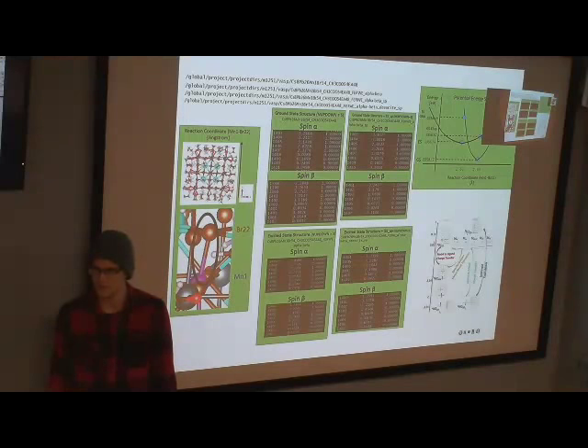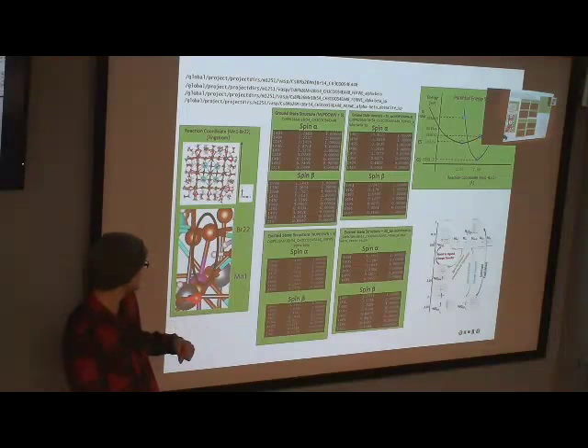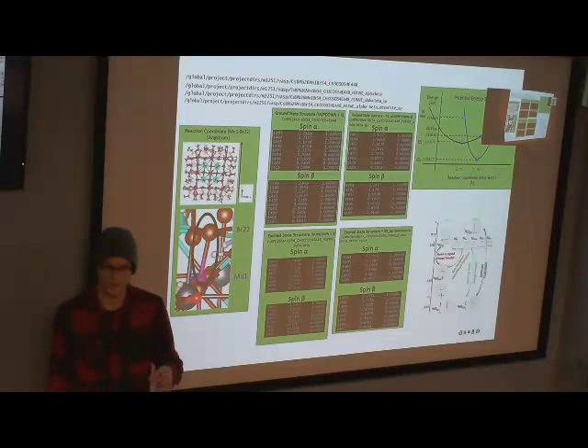Well, it depends on the transition that occurs, I guess. In this case, you have an optical transition occurring from the dopant to itself. And since it spin flips, the ground state has 5 electrons pointing up, so 5 up states. Then for an optical transition, since they're all in the up state, one has to flip to get into the other orbital. So you remove 1 up and add 1 down. Therefore, it changes by 2, from 5 to 3. Yes. Okay, makes sense.